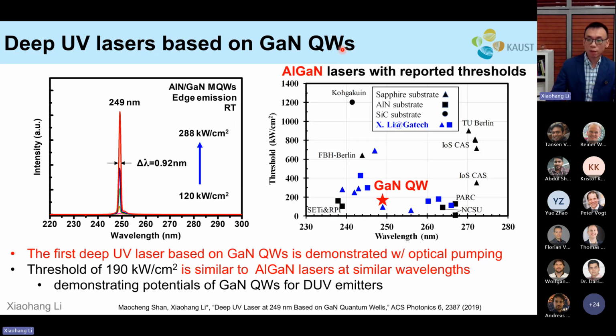If we do a little benchmarking with the AlGaN lasers which I showed earlier, you can see that our gallium nitride quantum well UVC laser actually has a pretty decent threshold compared to the reported AlGaN quantum well UVC lasers on various substrates. So this means that this material system is quite interesting and maybe promising for the further development of UVC lasers and LEDs.